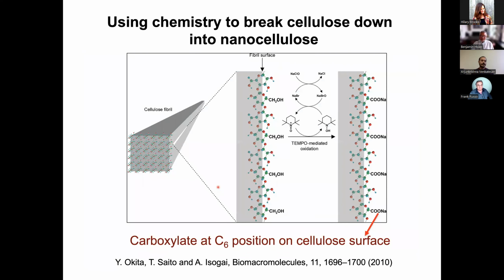And this is the chemistry of the TEMPO oxidation method, about 2010-ish, a famous work. This is a cellulose surface, and as you can see, there's a hydroxymethyl group right here. And there's two shorter hydroxyl groups here, but this one is sticking up a little bit more, more hydrophobic. So it can be selectively oxidized by this TEMPO-mediated oxidation process and become COONa.